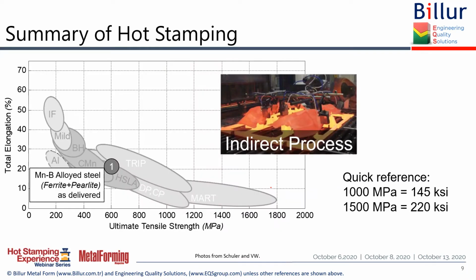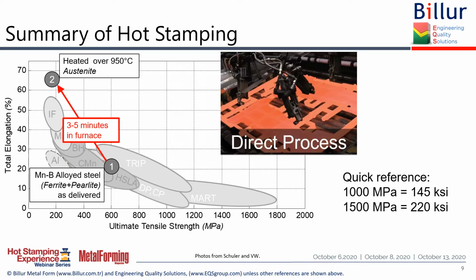Regarding PHS, the base steel that is used is sometimes referred to as an MNB, manganese boron alloyed steel, and comes from the steel mill as a ferrite pearlite product, or a product that has that microstructure. And that's where the indirect process is used. We'll be learning a little bit more about that in a handful of slides, but it's used in that condition.